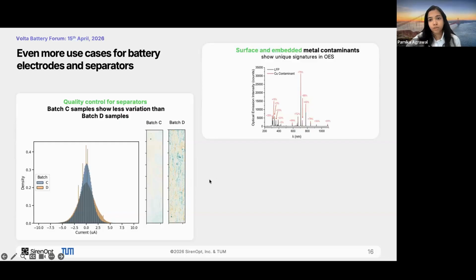The other very important use case we're working on is detection of metal contaminants. As many of you may know, these are killer defects. Defects as small as 50 microns can lead to thermal degradation of batteries and cause fires. So detection of these contaminants at an early stage, during the electrode coating stage, is super important. We are actively working on developing algorithms to detect metal defects.